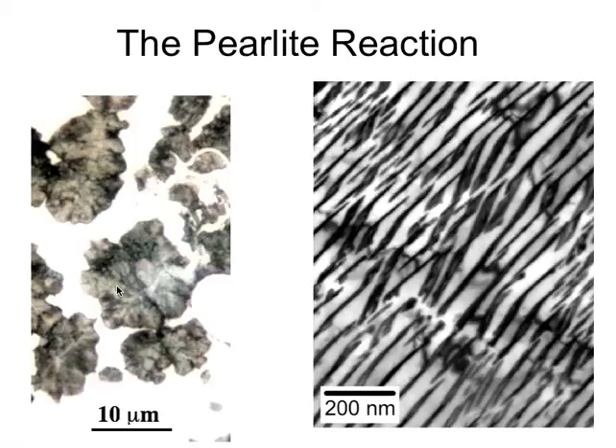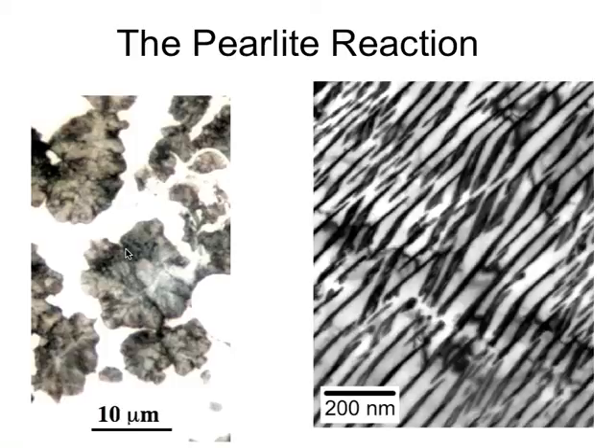Each of these colonies is actually a bicrystal of ferrite and cementite in three dimensions, and when we section it, it appears as alternating layers. This is quite important because although the strength is determined by the spacing between the cementite, the toughness is determined by the size of the pearlite colony — because if the crystallography is the same across the colony, the crack will not be deflected sufficiently within the colony.